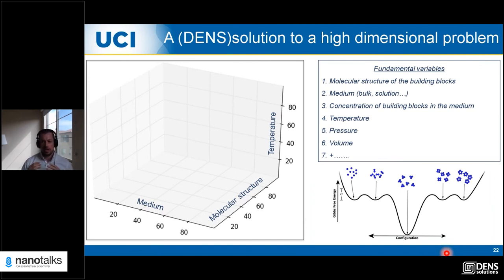From the in-flask experiments, every time we increased temperature by 20 degrees Celsius, we had a roughly order-of-magnitude decrease in the time it takes for silicon nanoparticles to be etched — from hundreds of minutes at 20°C, to tens of minutes, to sub-10 minutes at higher temperatures. When we did these experiments inside the microscope, we found exactly the same behavior: hundreds of minutes at 20°C, tens of minutes at 40°C, and just a couple of minutes at 60°C. Although there have been quite a few heating papers with different liquid cell holders, this is the first time anyone has shown quantitative agreement of the change in kinetics as you heat something up.